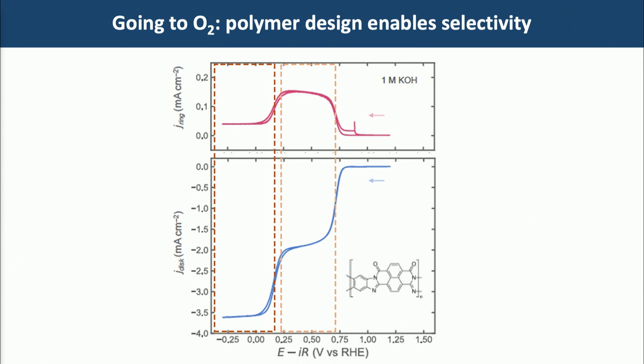So this polymer is called BBL, and you can see that within a certain potential window, the current is half. You see it between 0.25 and 0.75 is half of what it is between negative 0.25 and 0.25. And that's half because there it's doing a two-electron reaction, so that's hydrogen peroxide. At higher potentials, it's doing a four-electron reaction, so it's going all the way to water. So this is a nice way to show how the materials design can really give you selectivity and allow you to reach different products depending on how you operate the material, which is quite unique. And this is really a brand new area of application for these materials.